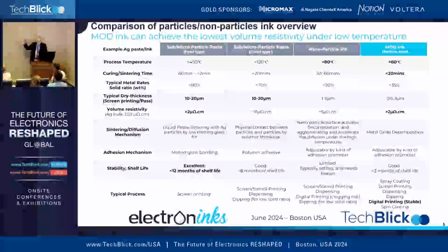Here's a chart that I'm not going to go through in its entirety. I would like to point out that the typical thickness after drying for the sub-micro particle paste is 10 to 20 microns, which is important. Nanoparticle inks only get up to 1 to 5 microns, and MOD inks are typically 0.5 to 3 microns in a single pass.